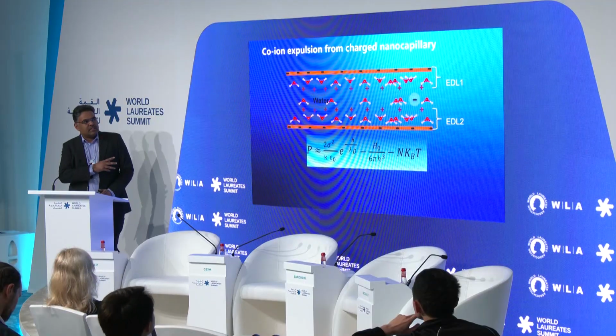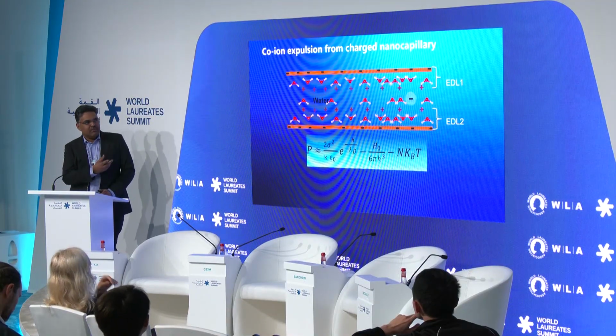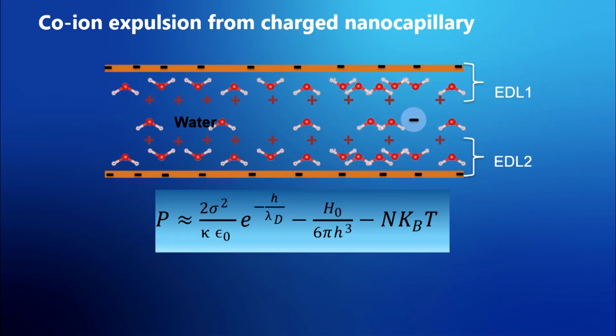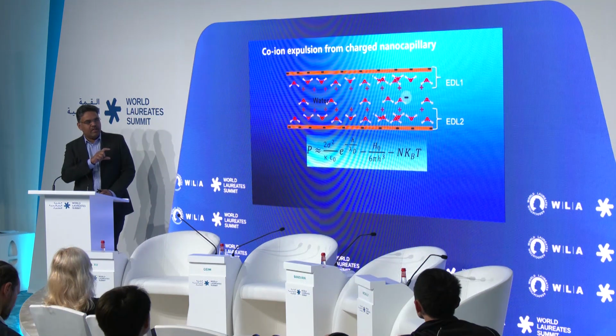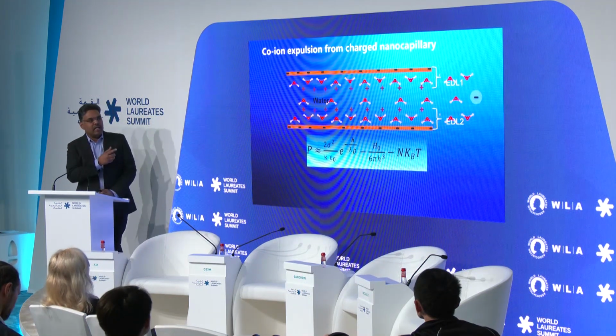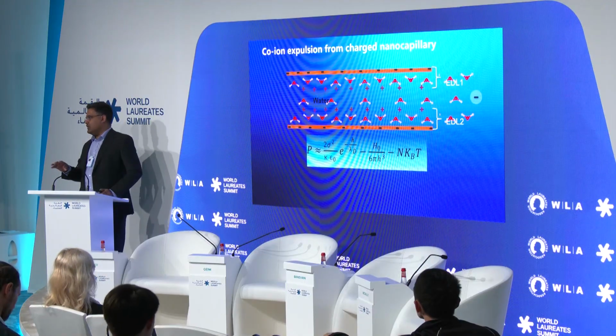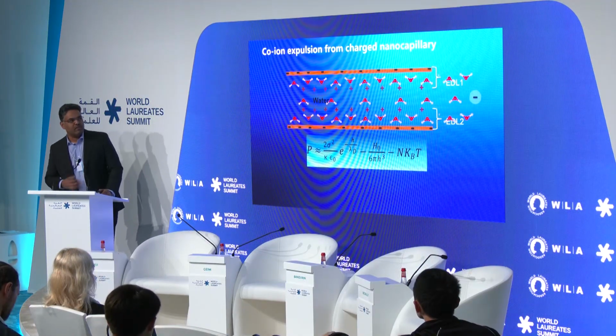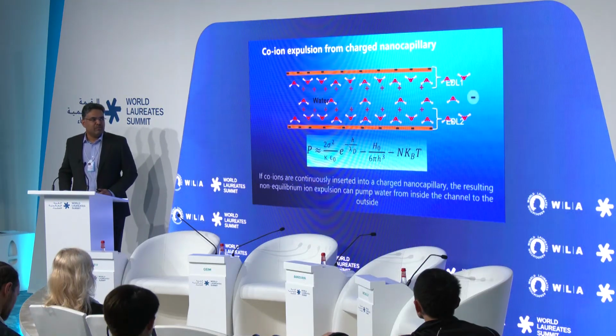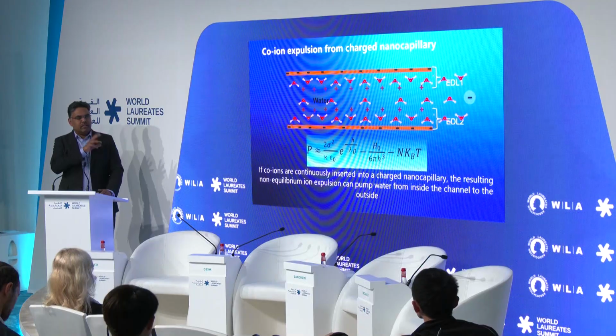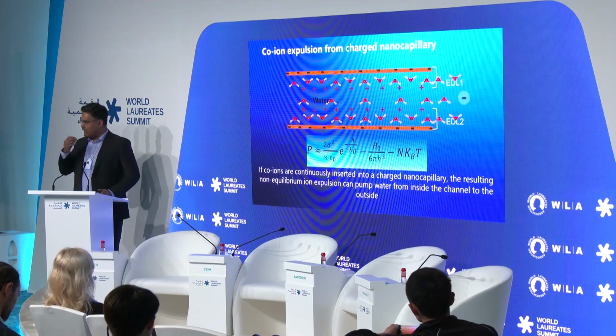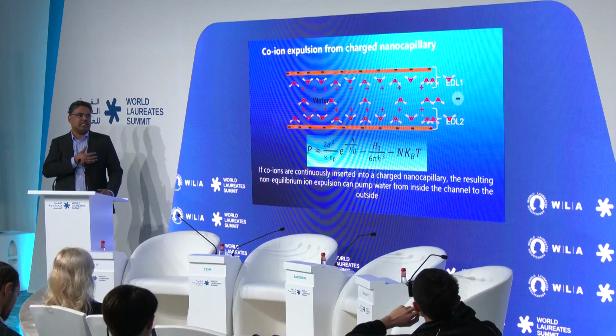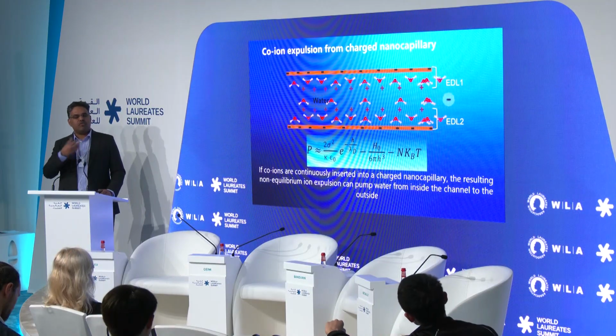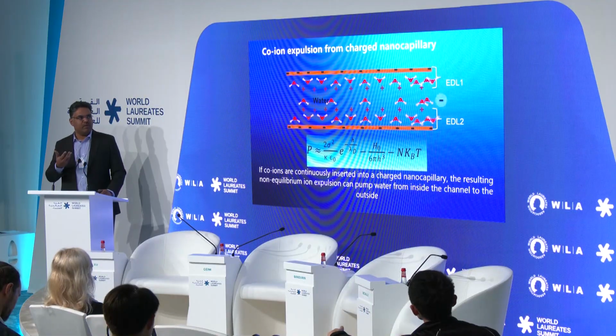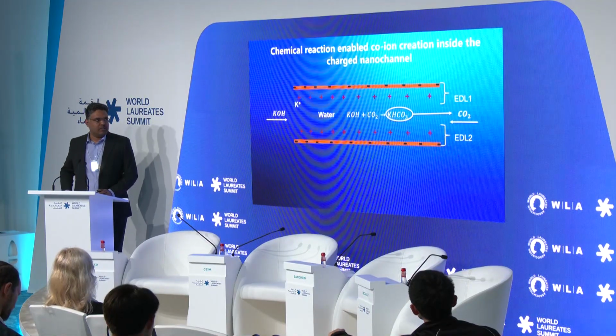In this process, there are three interaction-driven pressures that drive the water. One is electrostatic repulsion, which actually repels the ion from the capillary. The second one is the van der Waals attraction force between these graphene layers. And the third one is osmotic pressure, which is directly proportional to the number of ions coming out. If you take more ions, of course, more osmotic pressure will drive the water out. So this is what we did experimentally. If you can continuously run the ion creation inside the channel, that will drive water out from the capillary continuously as well. It is a non-equilibrium process, and then we will get a continuous process in practice.